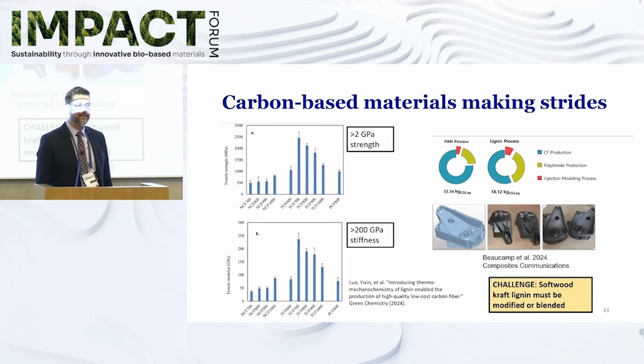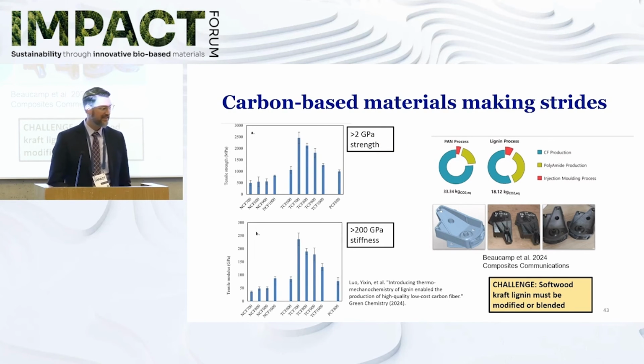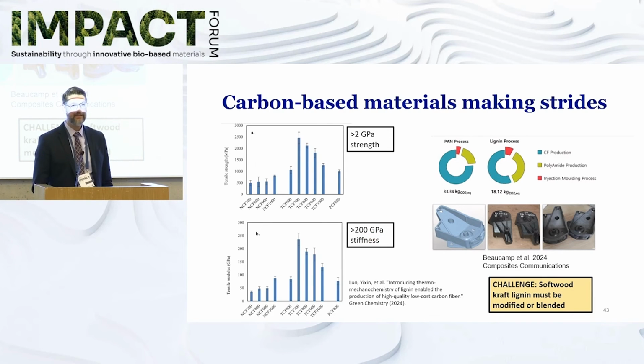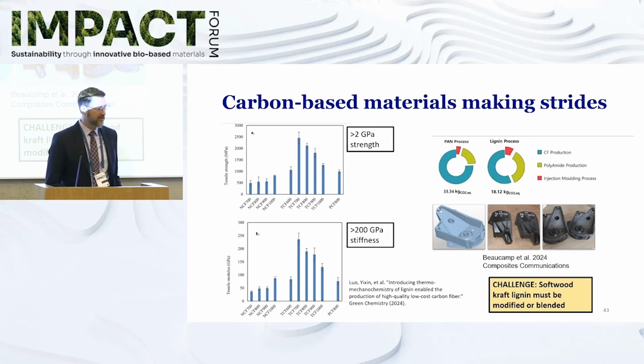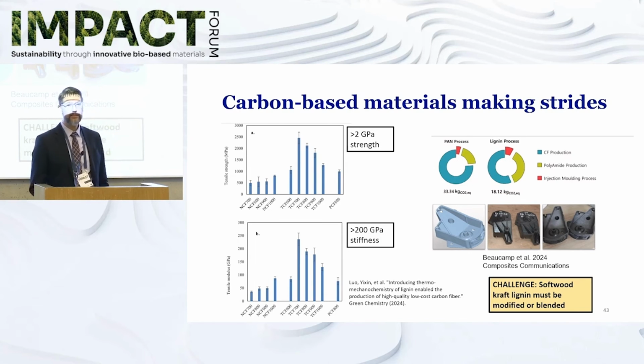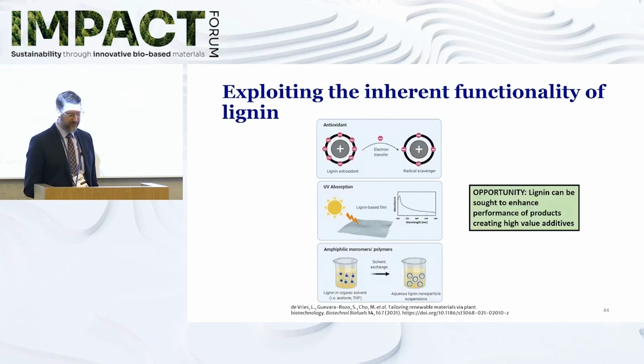Lignin can help out in this area. There's been some recent work from Purdue University where they found outstanding properties for lignin-based carbon fibers, in the range of 2 gigapascal strength and 200 gigapascal stiffness. These values far exceed things like glass fiber. They're not quite at PAN fiber levels, but we don't need those properties because we're not going to build airplanes out of this; we want to build car parts. Looking at the carbon footprint, there is a significant reduction, going from 33 kilograms equivalent down to 18 with the substitution of lignin-based carbon fiber. So there's hope there.